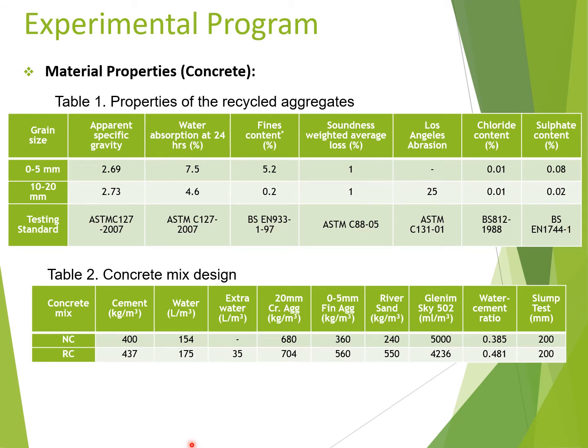The mixture proportions of the fresh concrete mixes are provided in Table 2. Owing to the high absorption of recycled aggregate concrete, there is an additional amount of water that was added to the mix to ensure workability. This was 35 liters per cubic meter. This amount was calculated based on the water absorption and the predetermined absorption capacity of the recycled aggregate concrete at 24 hours.